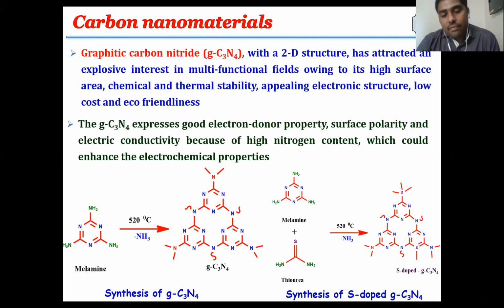Generally, graphite carbon nitride C3N4 is synthesized from nitrogen-rich aromatic compounds such as melamine by polycondensation process, and the electronic conductivity and electrical property of the graphite carbon nitride can be enhanced by the doping of heteroatom in the lattice of graphite carbon nitride.